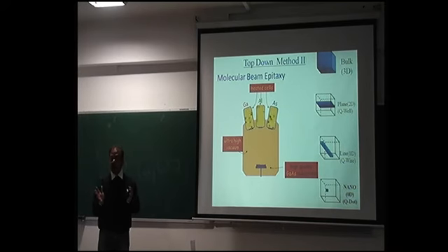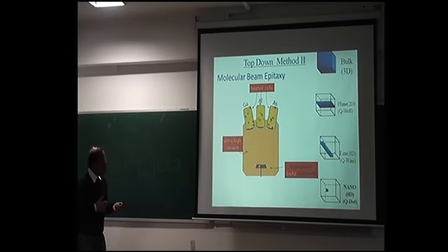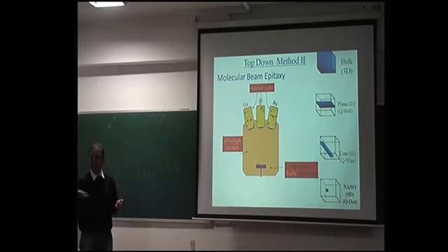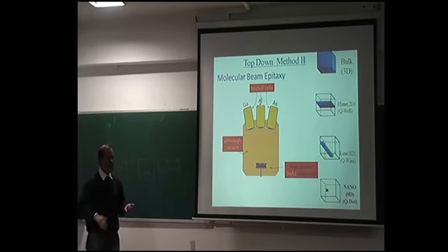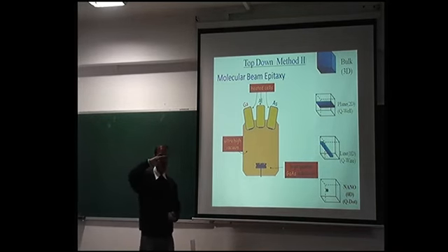Even for certain configuration, you can keep it open for 1 minute. You'll still get one monolayer. Okay? So one monolayer I got. Now this monolayer is gallium arsenide, where for growing gallium arsenide, I opened gallium and arsenic. Now I want gallium and aluminum arsenide. Now I'll open 3 simultaneously, and I'll get gallium and aluminum arsenide. This way you can make layer by layer growth.